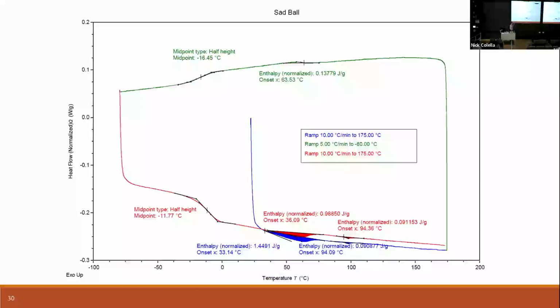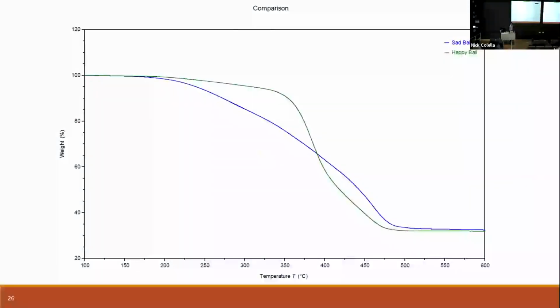But we can go to 550 for materials that are safe to run up to 550. PMMA and the polycarbonate. Yeah, so some more stable polymers we can heat up a little bit higher. And if we don't know, we'll do TGA first. So in general, if you want to heat past 220, I'll have you do TGA first so you can prove that your material is stable up to the temperature that you want to run to in the DSC.